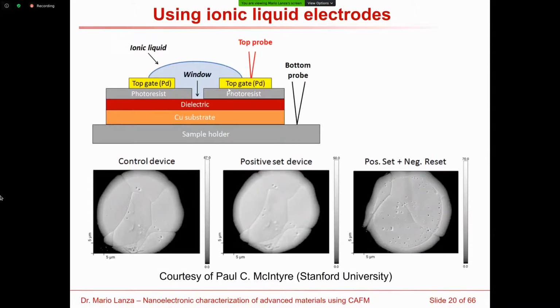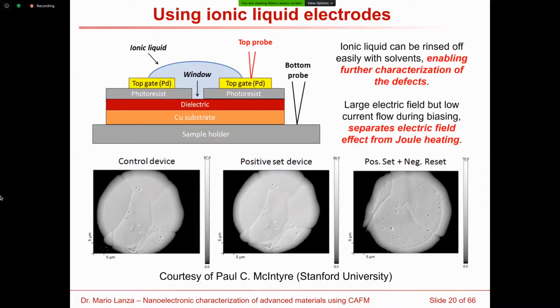So basically, the structure looks like this. We use a very thick photoresist with some top electrodes on top, and we put one drop of the ionic liquid that contacts both the dielectric window and the top electrode, and we apply some electrical stress with the top probe at the probe station and the bottom probe. Here we can stress the dielectric, and the beautiful thing of this method is that we can rinse the ionic liquid, and after that we scan the bare surface of this dielectric with any technique we want.